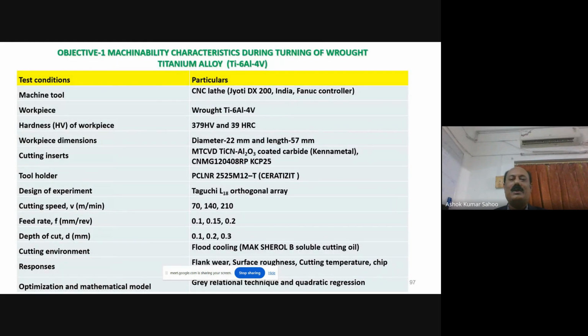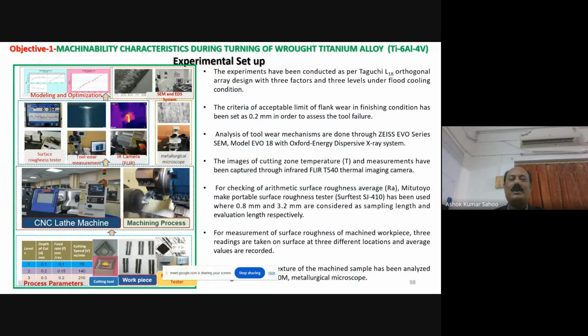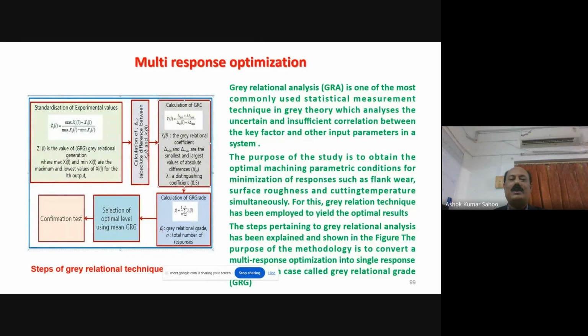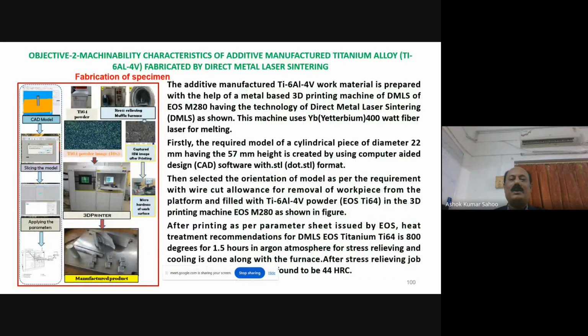So this is the experiment conducted for the wrought titanium alloy, and the experiment has been designed through the Taguchi L18 orthogonal array by taking three process parameters, cutting speed, feed, and depth of cut, with three levels, 70 to 210 meters per minute cutting speed, and is operated in a flood cooling environment. This is the experimental setup for the machining of wrought titanium alloy, optimized through grey analysis.